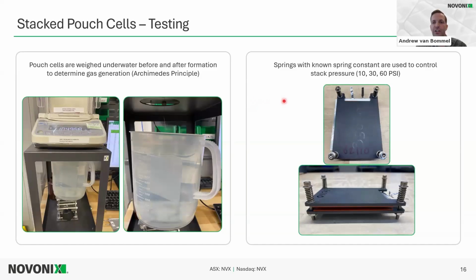For our fixturing, we fixture the cells. So we have two plates here, an upper and a lower plate. And there's springs with a known spring constant applying pressure to the stack. By varying the height of the spring, we can vary the pressure applied to the stack. So typically when we're testing NMC graphite cells, we run around 10 psi. If we're doing silicon cells, we might go 30 or 60 psi, depending on the amount of silicon in the anode.